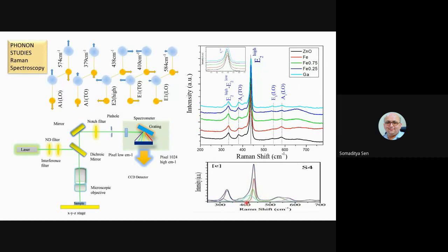original data. And what we have done, we have fitted the data using a software called FitYK. This FitYK takes different peak forms, Gaussian, Lorentzian, or Voigt, which is a mixture of Lorentzian and Gaussian, and tries to fit this data. By fitting the data, you can know what type of frequencies have what type of intensity, so how many modes are activated in that form.